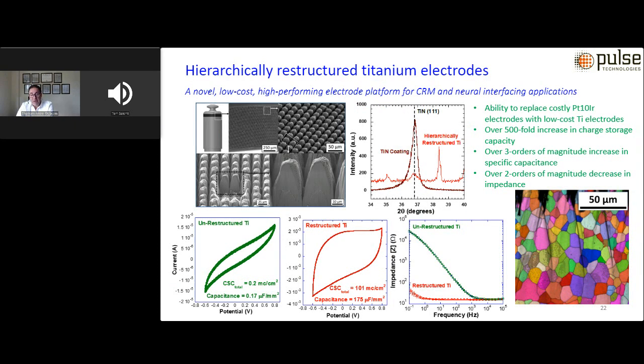So I'm really proud to say that we've developed a proprietary process that can hierarchically restructure high-performing titanium electrodes as a low-cost alternative to platinum-based electrodes. The technology offers numerous benefits over titanium nitride coatings that are traditionally used in CRM, or cardiac rhythm management, applications as a coating on platinum-based electrodes. The technology has essentially redefined the CRM electrode technology because it offers many, many benefits.